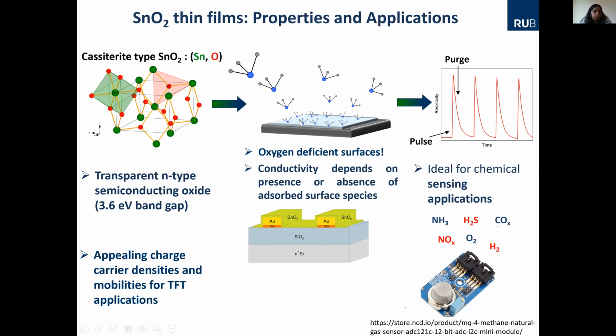So you can absorb certain gases, and when you measure the resistivity as a function of time and you pulse a gas, then you can see these variations. Typically this material can be used for chemical sensing, for example ammonia, H2S, hydrogen, or CO. That is one of the outgassing materials in automobiles, in our cars. So this is where it's getting more and more relevant.